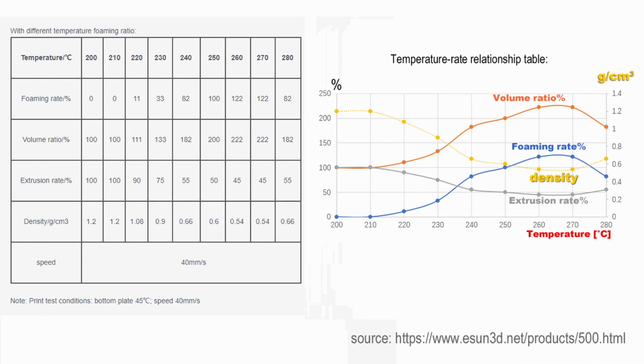If we look at this table, which shows us the temperature between 200 and 280 degrees Celsius, for me two lines are most important here. You can see the extrusion rate at 200-210 degrees Celsius is 100, and in this case the density will be as a regular PLA of 1.2 grams per cubic centimeters. But above this, the foams start to be created, and we can reduce the extrusion rate, and with this the density will be lowered also.